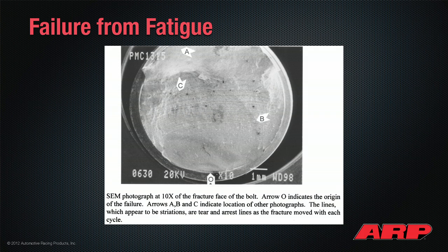So you can see these striations going across here. Each time the joint gets to a load that exceeds the clamping load within the bolt, it's going to open that crack up. On the downstroke, it's going to close back because the load is relaxed. As it gets to top dead center again, that crack's going to open up. And that crack keeps opening up and ratcheting. And these lines show the travel of that crack. And you can see we've got to the point here where you've gone more than 50% across the face. So you've got a very, very tough ductile material here.